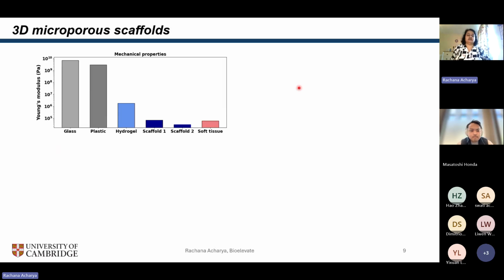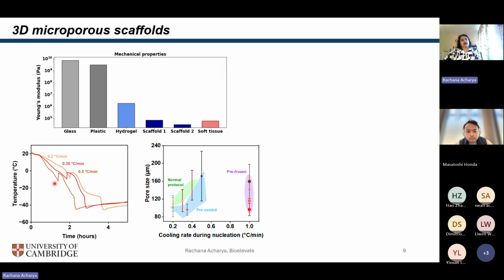So that's a success. Not only that, because of the mechanical properties of the polymer, we are much closer to the mechanical properties of tissue as compared to glass and plastic. So that's another win. And as I showed you the freeze drying process, I can change the freezing rate or the cooling rate and basically alter the nucleation and growth of ice crystals to have scaffolds of different pore sizes. So that's how we can also tune the size and the morphology of these pores for different applications or for different organ models.